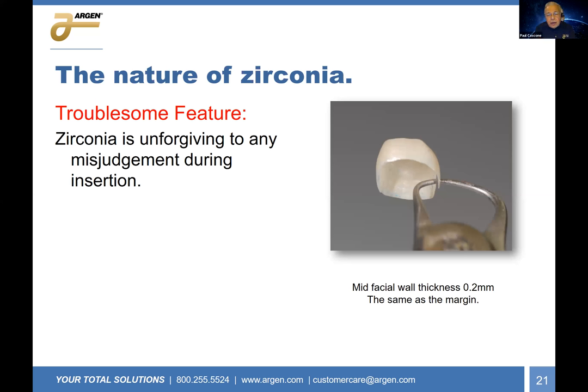Here's a case of not flexing. There was a small misjudgment during insertion, and the wall just cracked away. Now, if this was a PFM, it probably would have survived because the metal would actually flex before the porcelain would crack. But in this case, with zirconia, that doesn't happen. It just cracks.